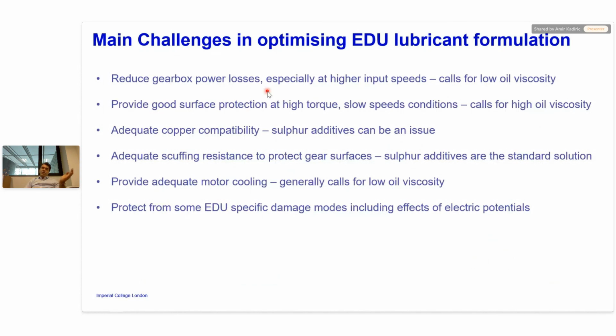Now, on the other extreme, when you have very low speed or you're just moving off with an electric vehicle, you're producing a high torque just due to the torque speed characteristic of an electric motor. Now, to protect the surfaces under those conditions where you cannot rely on a thick enough hydrodynamic film, you really need a higher oil viscosity. You need specific formulation of an oil to protect the surfaces in boundary and mixed lubrication. So you have an issue here because on the one extreme you need low oil viscosity, on the other extreme you want high oil viscosity.